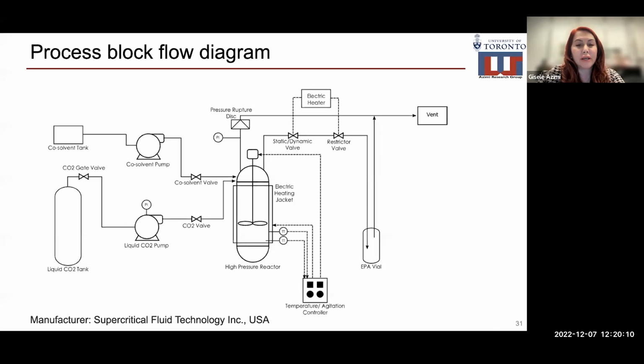This is the process flow diagram of our process. The reactor was manufactured by Supercritical Fluid Technology, Inc. in the United States. We place the feed and a small amount of a chelating agent on top. We close the reactor. The liquid CO2 is pumped inside the reactor. Sometimes we add some co-solvents to the reactor. Then the pressure and temperature are raised above the critical point. When we reach the set temperature and pressure, sufficient time is allowed. And after that, the system is depressurized, the sample is collected in a collection vessel, and the CO2 leaves the sample because of depressurization.